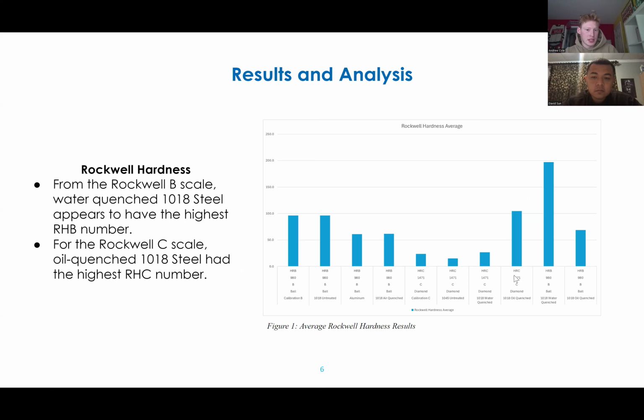And for our results and analysis. So from the Rockwell B scale, it appeared that the water quenched 1018 steel had the highest HRB number. And for the Rockwell C scale, our oil quenched 1018 steel had the highest HRC number. It should be noted here that for the oil quench and the water quench samples, there were both Rockwell B and Rockwell C samples. And we have a very, very high number for our 1018 water quenched for our Rockwell B scale, which indicates that it might be better suited for a C scale to get more accurate results.